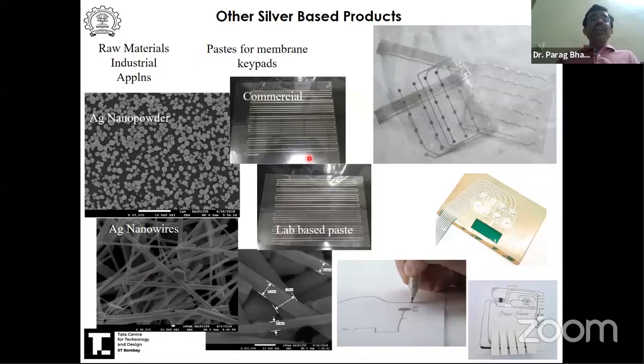Another thing that we make in our lab is another kind of paste, which are room temperature pastes, and we can print them on polymers. Like this kind of pattern is there in every computer keyboard. If you open up some used keyboard, you will see that there are these membranes, 2 polymer membranes, PET, on which you have silver patterns. So when you press a key, basically you are connecting these silver patterns so that your action happens in a computer. Or in many other devices, you have these silver printed circuits and patterns. So we make these pastes. This is a commercial paste which is printed in our lab, and this is our own paste. So we are able to print it nicely.